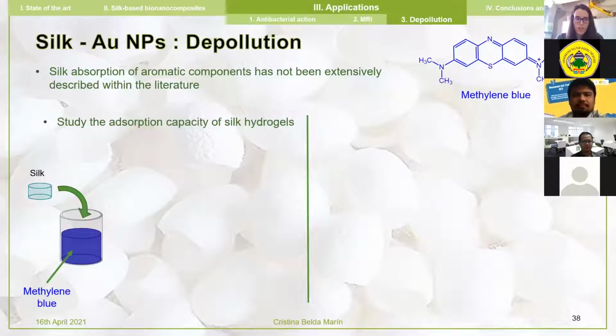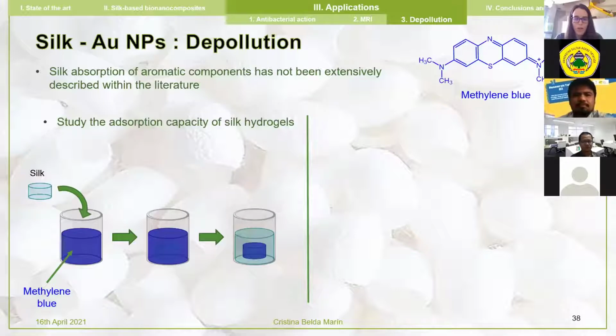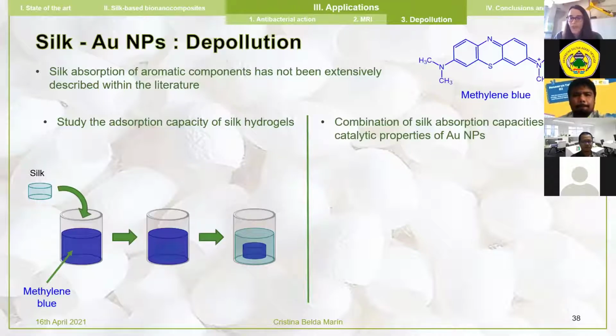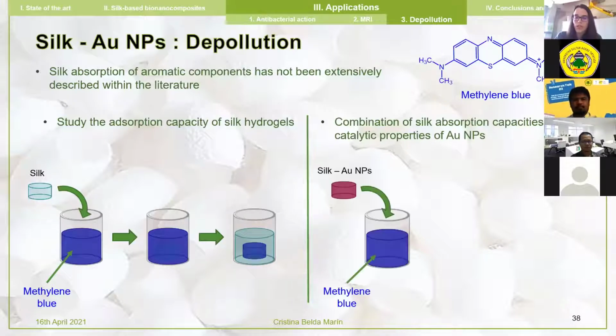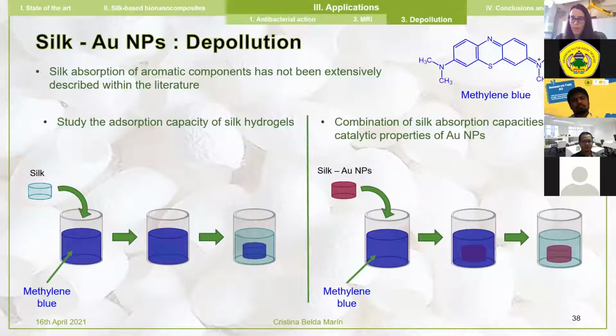And to do this, we are going to get our silk hydrogel and place it into a methylene blue solution. And over time, we're going to see that actually the entire methylene blue is absorbed within the silk hydrogel. Then we want to combine this absorption capacity with the catalytic properties of gold nanoparticles. Here, the idea is slightly the same. This time we are using our silk gold nanoparticle bionanocomposite, introducing it into methylene blue, and then over time, methylene blue will be degraded.